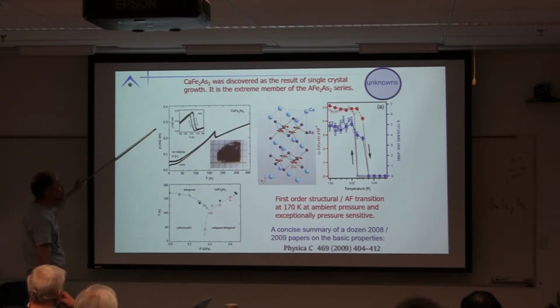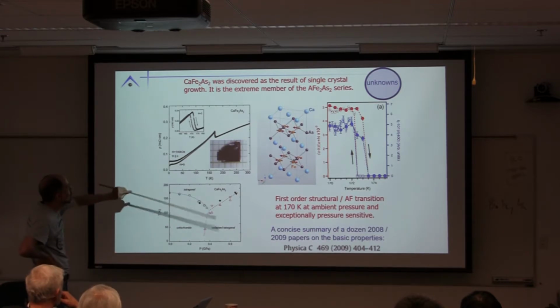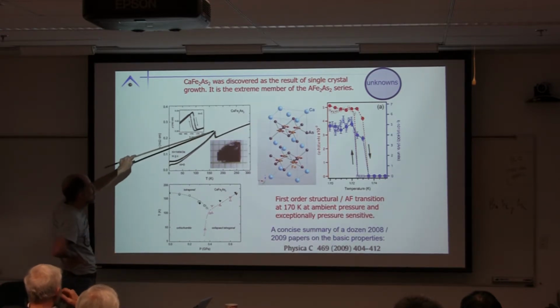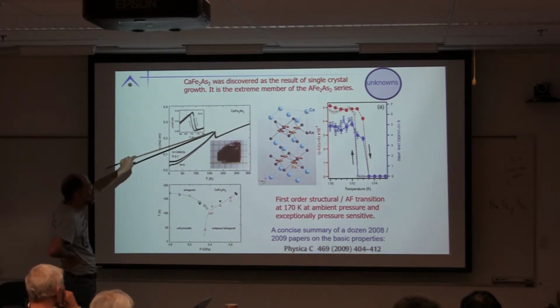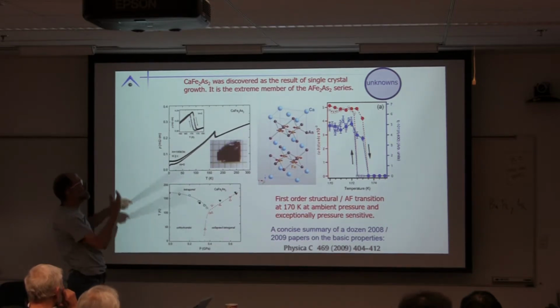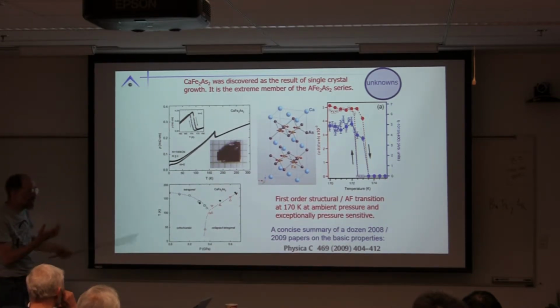So we could grow this nicely out of tin. You can also grow it out of iron arsenic. You can get beautiful crystals. It has a sharp, strongly coupled first order structural and magnetic phase transition, and it actually has become the extreme member of this 1-2 series, and more importantly, and at the end of this talk I hope to get to, the springing off point for looking at other related series.